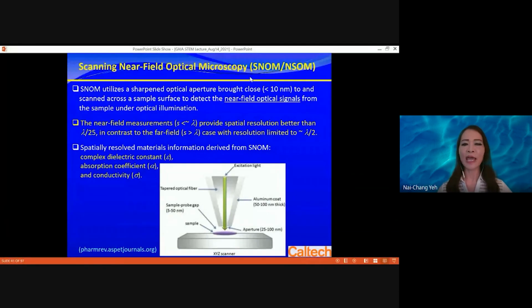And then we can also consider light. There are very interesting light properties. You want to study light, but usually the wavelength is very long. Visible light has several hundred nanometers in wavelength. So how do you go to nanoscale resolution? The trick is that you go to near field. When you bring an optical fiber very close to the sample, near field can give you a resolution much better, one order of magnitude better than the far field resolution. In far field, you are dictated by the wavelength.